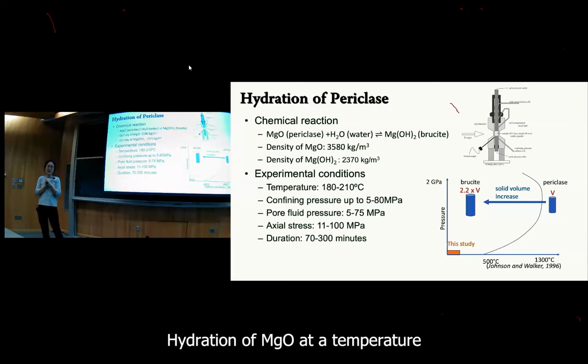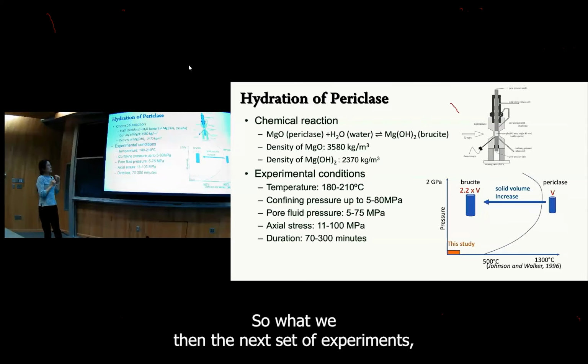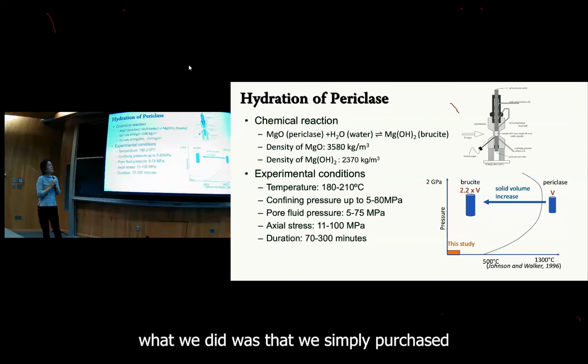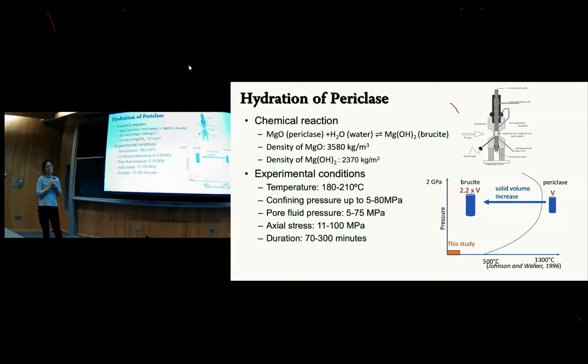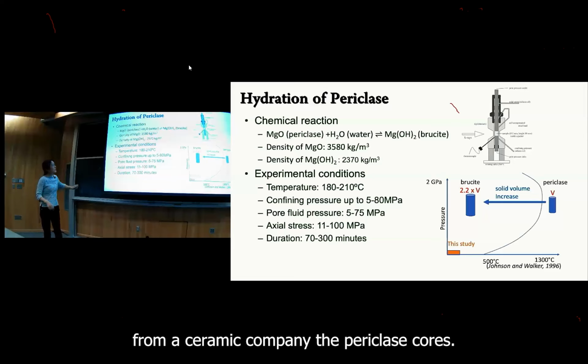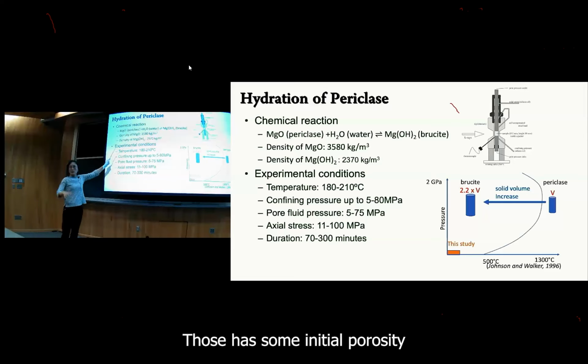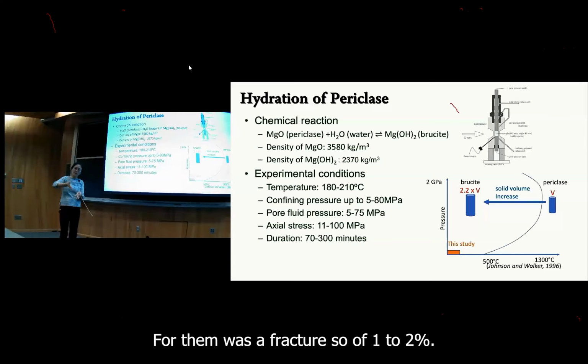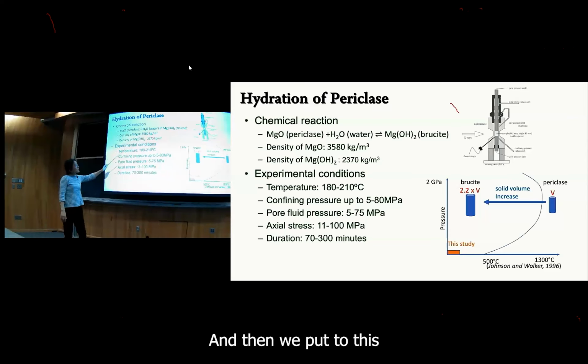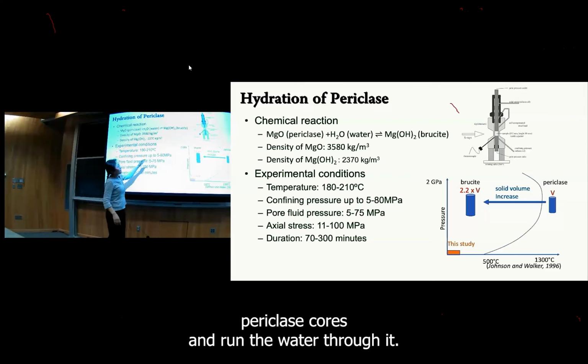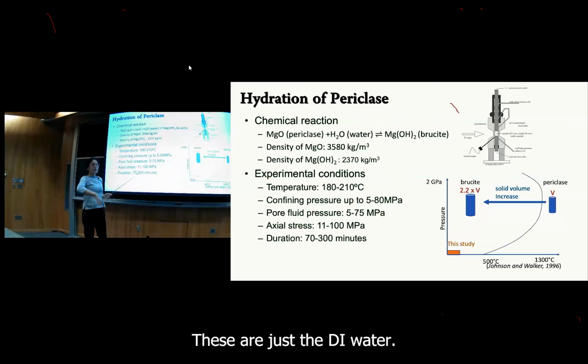Hydration of MgO at a temperature above 150 C can be very fast. So for the next set of experiments, we simply purchased periclase cores from a ceramic company. Those have some initial porosity, which acts as a defect for them, with porosity of 1 to 2%. And then we put these periclase cores in and run the water through them. These are just DI water.